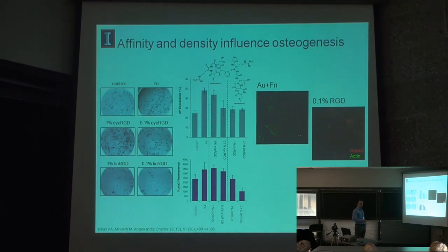So we did some other staining. This is for RUNX2, which is a master osteoblast regulator. And we see a peak in the RUNX2 expression. And this is normalized nuclear to cytoplasmic fluorescence. And we see that for cells on the cyclic peptide and the fibronectin, we see higher nuclear expression of RUNX2, indicating that you have more of a proportion of lineage active RUNX2. So we also isolated RNA from this to verify our immunofluorescence results. And so we got RNA and we profiled these and found that we got the same sort of trend. Here for alkaline phosphatase, we see robust expression on cells on fibronectin, on cyclic peptide, but then a significant decrease in expression on the linear peptide. And a similar sort of trend we saw for RUNX2.